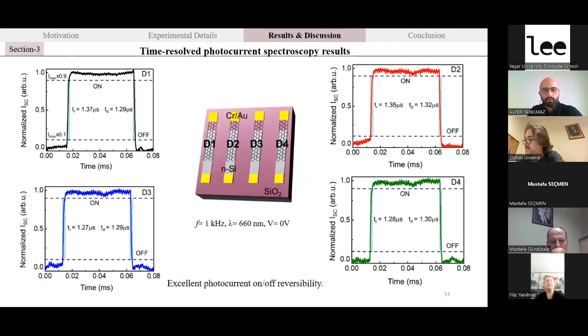The time-resolved photocurrent measurement was also done for each diode. Here you can see the rise time and the fall or decay time of these individual diodes is nearly 1.3 microseconds and 1.3 microseconds respectively, under the self-powered condition. All diodes show excellent photocurrent on-off reversibility, and this is also an important result of the study.